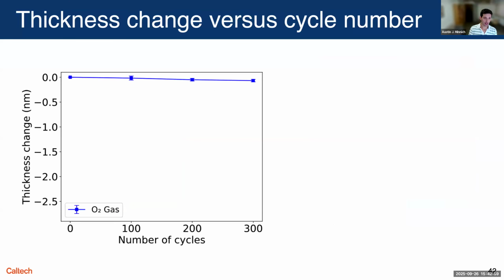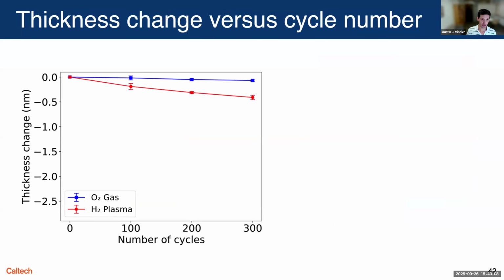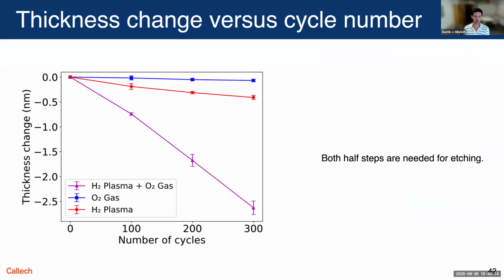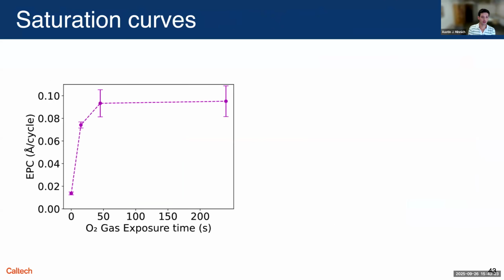Now, when you do this, we can look at these half-cycle thickness changes versus number of cycles. So when you only expose to oxygen, basically nothing happens. When you only expose to the H2 plasma, a little bit happens, but not much. But when you do both of them together, you get a measurable thickness change. So that's the key requirement for ALE. The other requirement is that after enough exposure of either component, you should not get an increase of etching. So that means the etch saturates with enough exposure to the different reactants. That's known as a saturation curve.